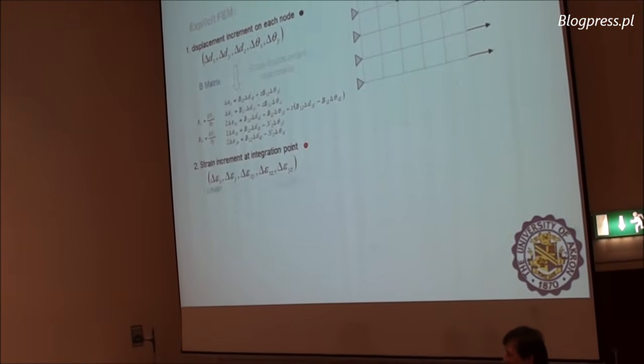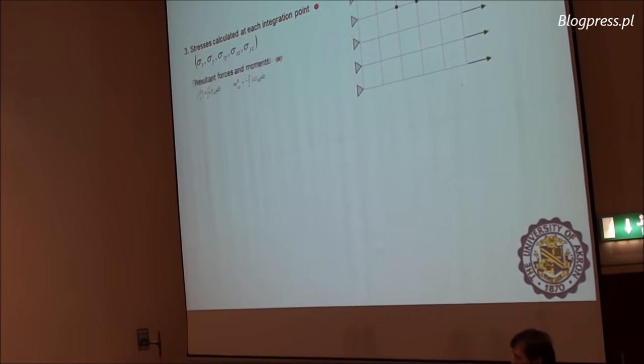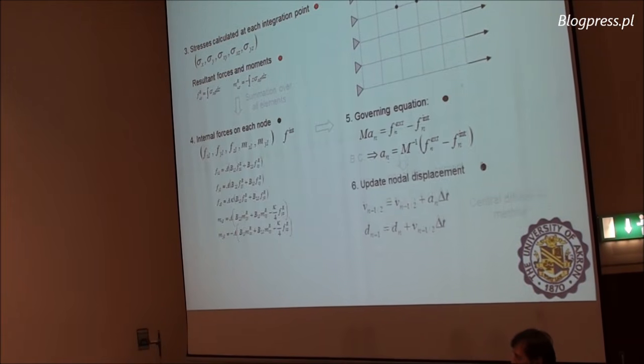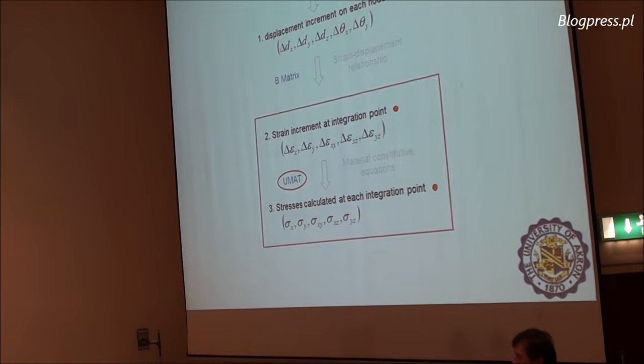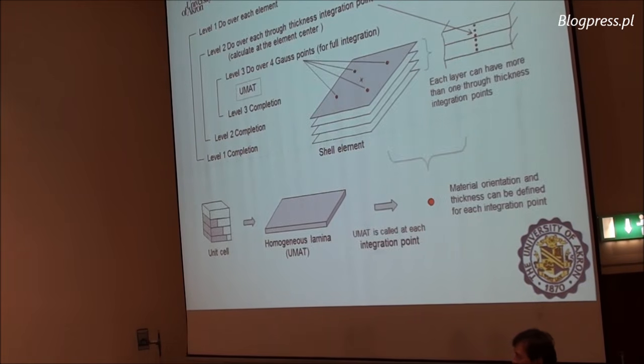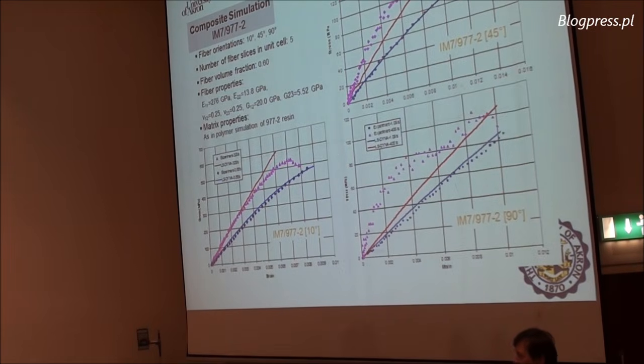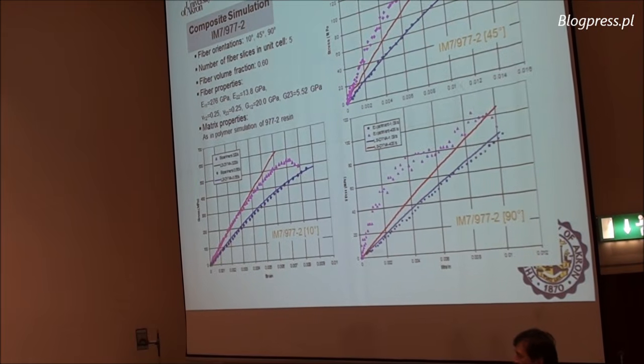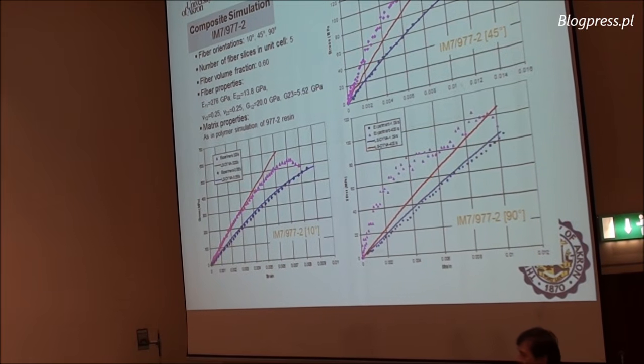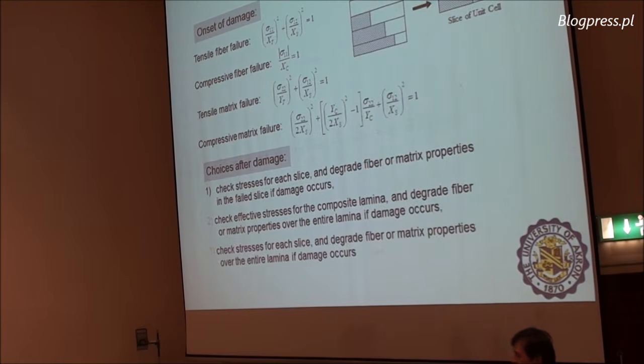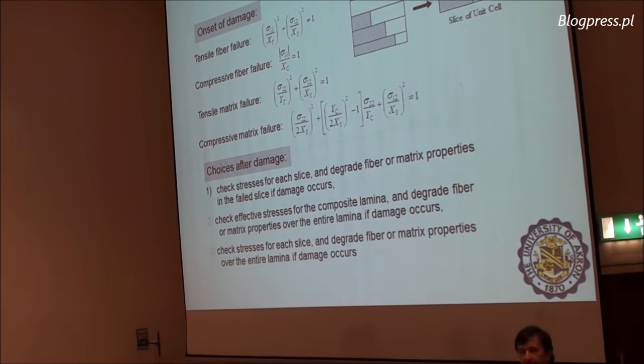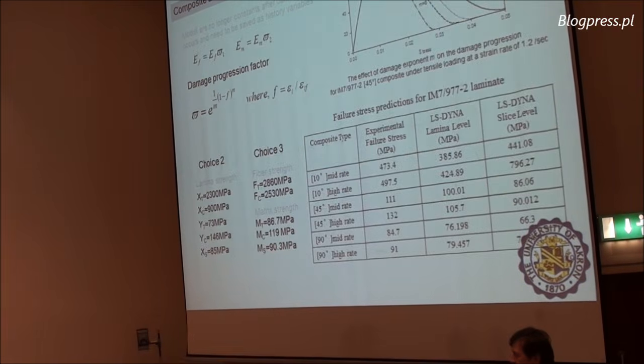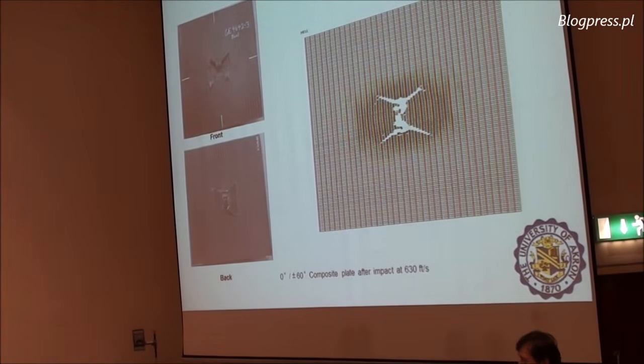This is the system of UMAT applied at the integration point, which basically takes the behavior of the resin and failure using the micromechanical model, and these are the results of the simulation with respect to experiment, which are satisfactory for us. And again, you can see the damage model using the so-called slice model that we use to incorporate and get the final results.